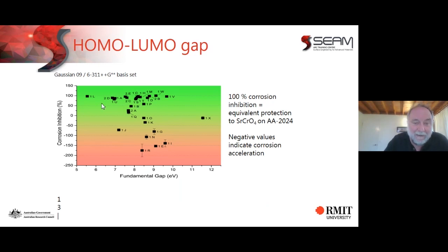And unfortunately, we found that when we plotted corrosion inhibition against this fundamental gap, we found virtually no correlation at all, despite what was in the literature. So this doesn't mean that it's not important, but it's not sufficiently important to describe the variation that occurs in corrosion inhibition. So then we look at, well, how else can we model corrosion inhibition?